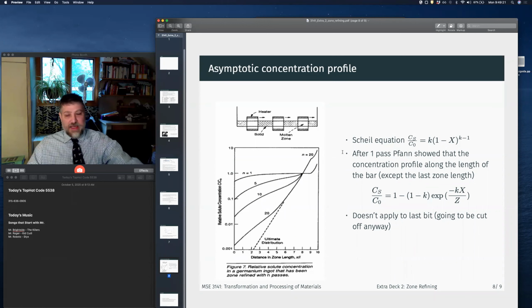So it's not super fast, right? You need to move the heater at, not slow, but you need to give time for the solute to move around. So this is not a super fast process, but it can be done on really long ingots. Essentially what you can see here is you can have multiple heaters traversing, so you can have multi-zone refining. You can imagine having like 20 of these things set up, and having a crystal ingot just continuously fed through here.